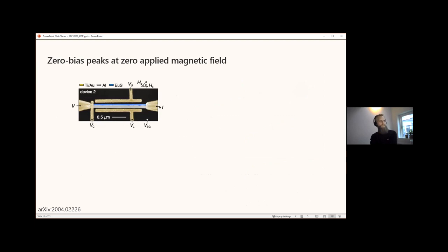We fabricated the following geometry, very similar to the previous tunneling device that I showed before, except here it has the tunneling barrier that crawls over the wire to increase the lever arm. It also has the upper and lower gate voltages to tune the density on both sides of the wire. And finally, it has a back gate that extends under the wire and also the junction. So essentially, the voltage on the back gate tunes both the charge density in the wire, but also the coupling